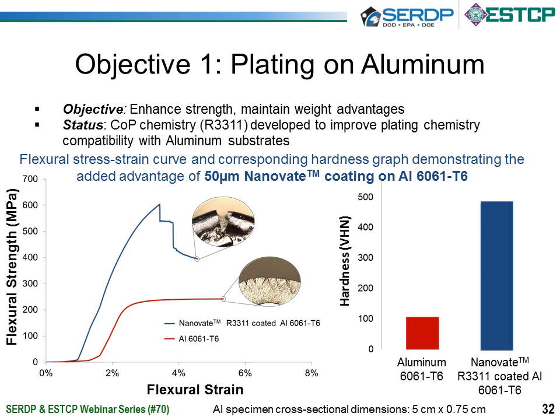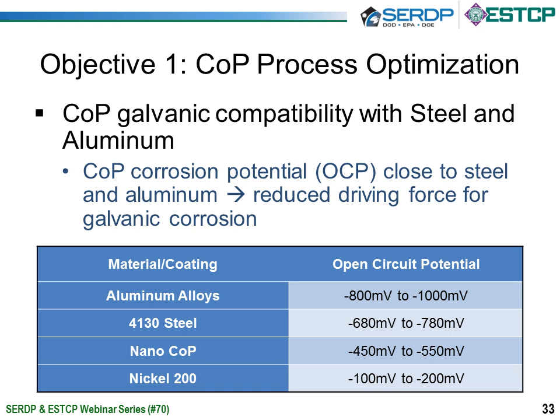So the other advantage of the cobalt-phos when looking at coating steel and aluminum substrates compared to nickel and chrome is the corrosion potential of the cobalt-phos. The open circuit potential is closer to that of steel and aluminum, so ultimately likely resulting in a lower driving force for galvanic corrosion between the coating and the substrate. Ultimately, hopefully leading to better long-term corrosion performance.